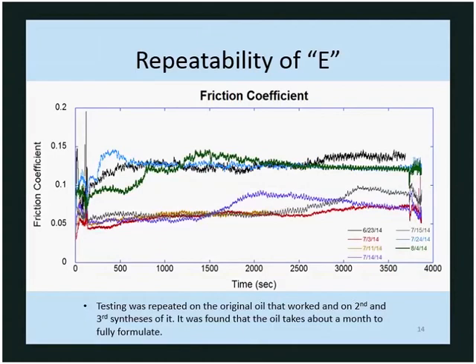And then repeatability of this one oil, to make sure that it was not just a fluke experiment. The testing was repeated on the original oil that worked, and then a second and third synthesis was performed. It was found that the oil takes about a month to fully formulate, and my time at the lab was done before the 1 month was over to formulate the oil. So that's why there's such varying results here. However, in due time, the friction coefficient should be around 0.05, but that just requires more testing.